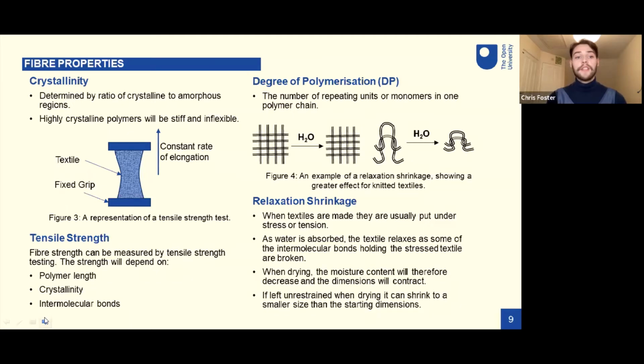You have the textile or fibre clamped between two grips, one which is fixed into place and one which moves at a constant rate of elongation. And we can actually look at the point at which the textile or the fibre breaks, and this is noted as the tensile strength. Now, this strength can depend on many different things, including polymer length, the crystallinity, intermolecular bonds, and the actual structure of the fibre itself.